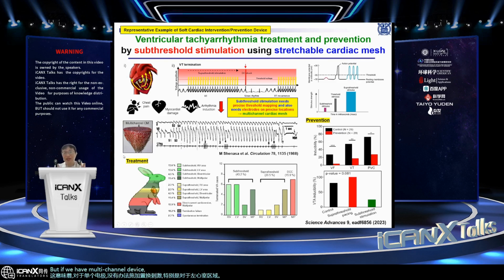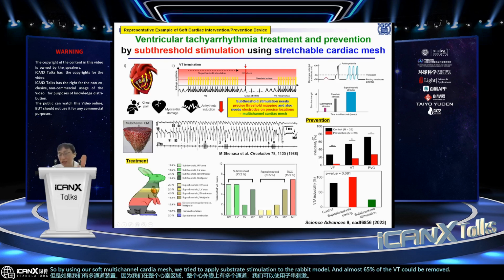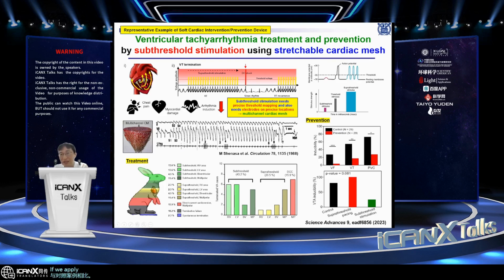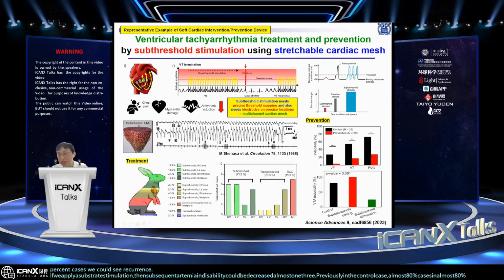But if we have a multi-channel device, since we have multiple channels on the entire ventricle region, the entire epicardium, we can use subthreshold stimulation. So by using our soft multi-channel cardiac mesh, we tried to apply subthreshold stimulation to the rabbit model, and almost 65% of the VT could be removed without DC shock. But more interesting is the result in prevention. In comparison to the control case, if we apply subthreshold stimulation, then subsequent arrhythmia inducibility decreased almost to one third. Previously, in the control case, in almost 80% of cases we could see recurred arrhythmia. But with subthreshold stimulation, that decreased below 30%. So it is a dramatic effect in terms of prevention of subsequent arrhythmia. That is very important.